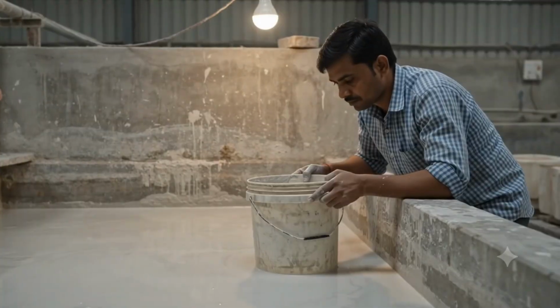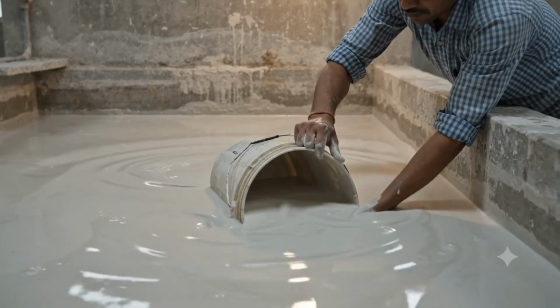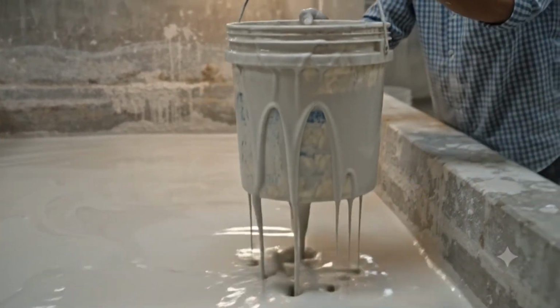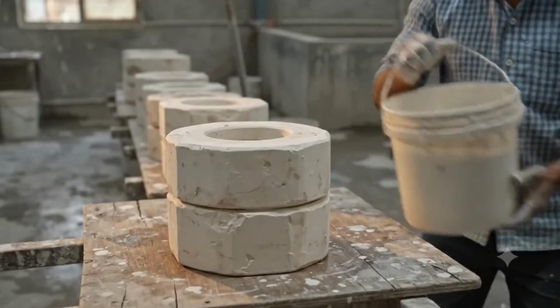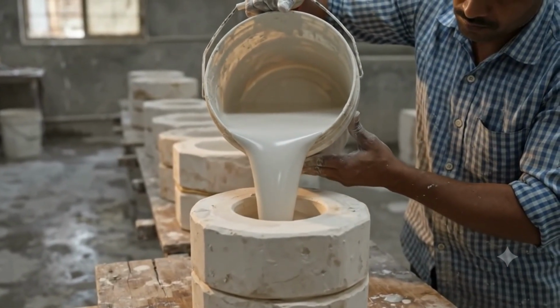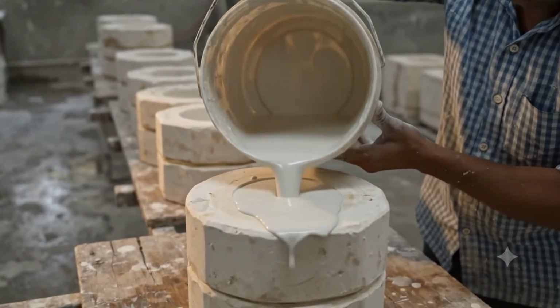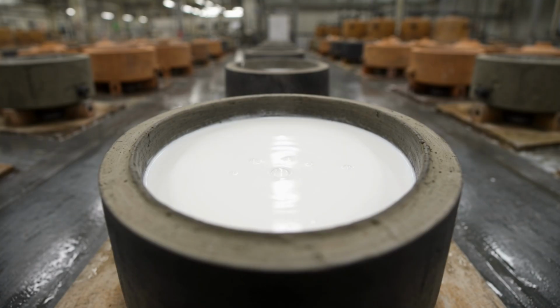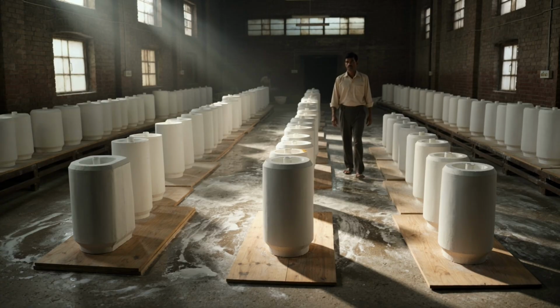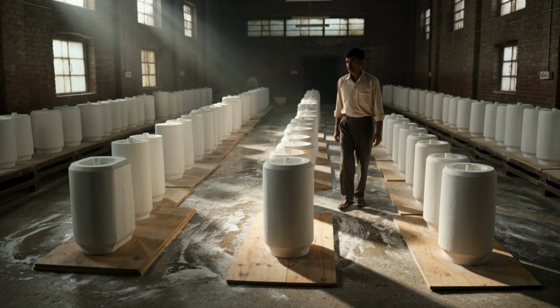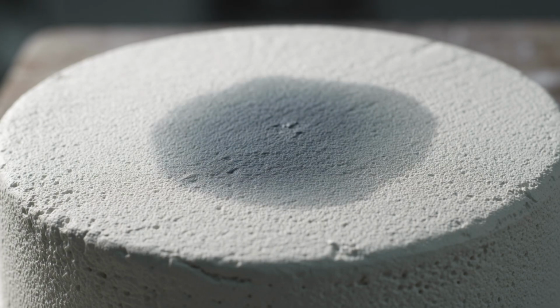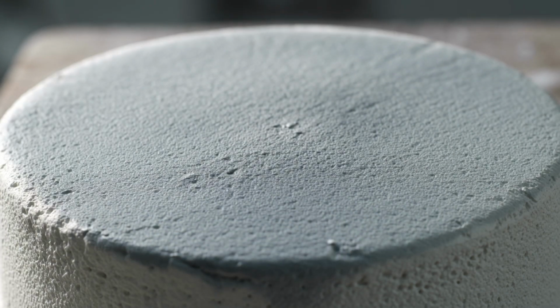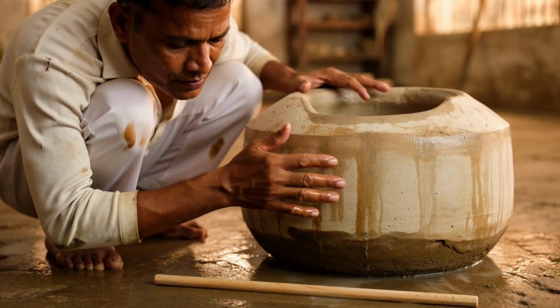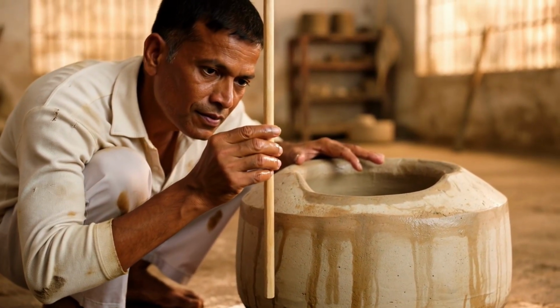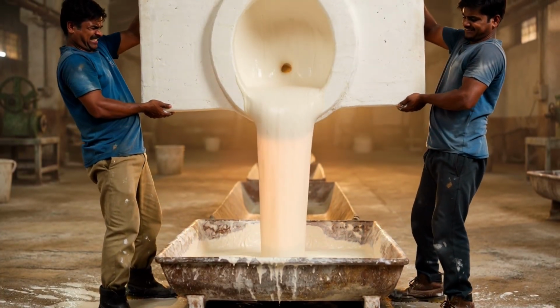Then, everyone waits. This is where the magic of plaster molds comes in. Plaster is naturally porous, which means it slowly absorbs water from the liquid slip. As the water gets pulled out, a layer of solid clay starts forming on the inside walls of the mold. The longer the slip sits, the thicker that clay shell becomes. Workers check on the molds regularly, tapping them and measuring the wall thickness to know when it's right. When the shell is thick enough, usually after several hours, workers tip the molds upside down and let the remaining liquid clay pour back out into the tank. Nothing gets wasted. That excess slip goes straight back in to be used again.